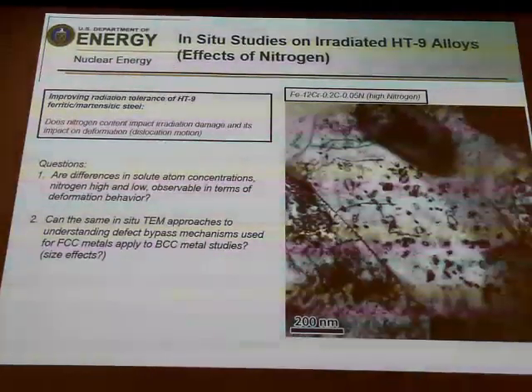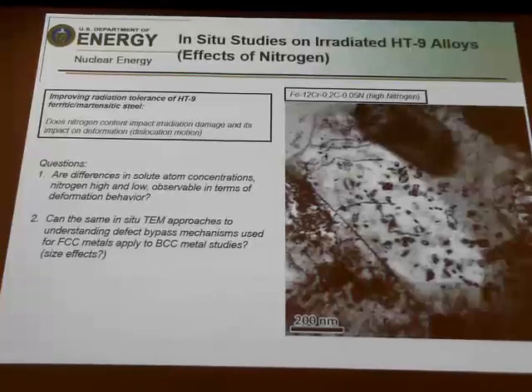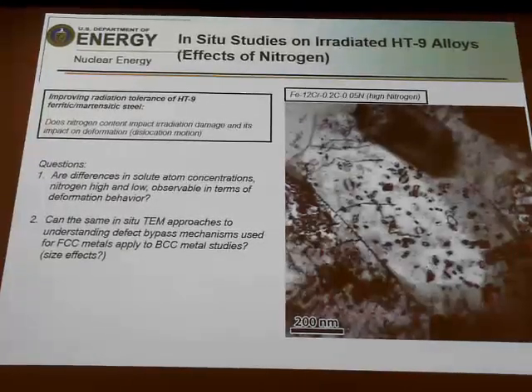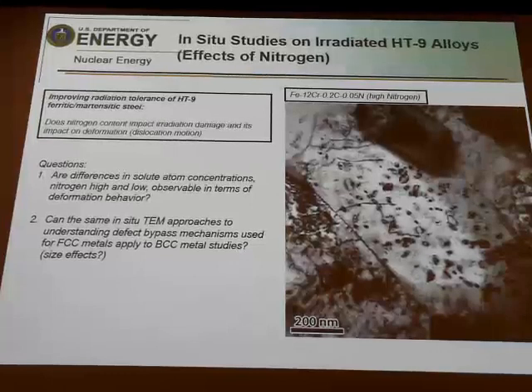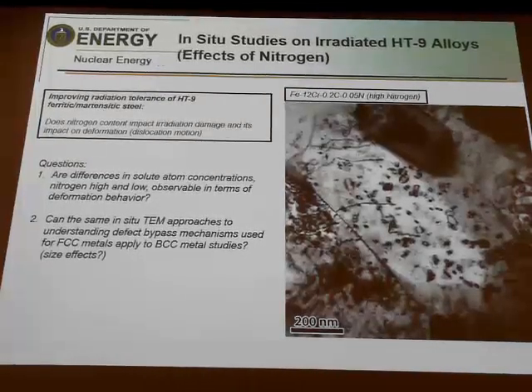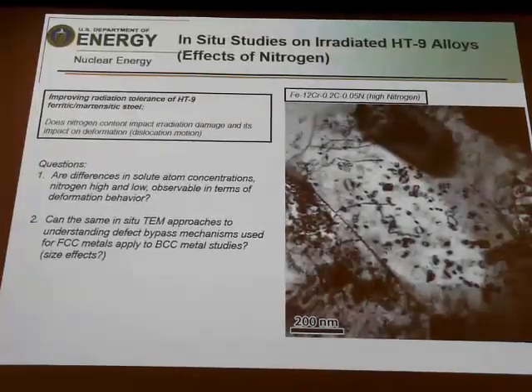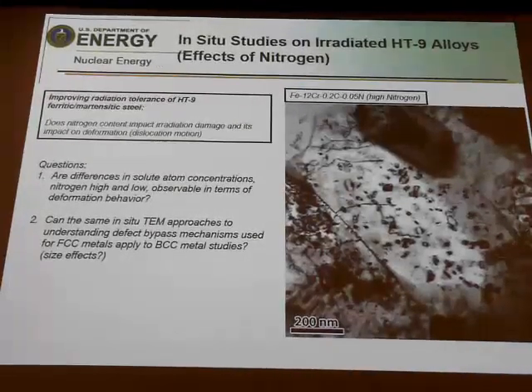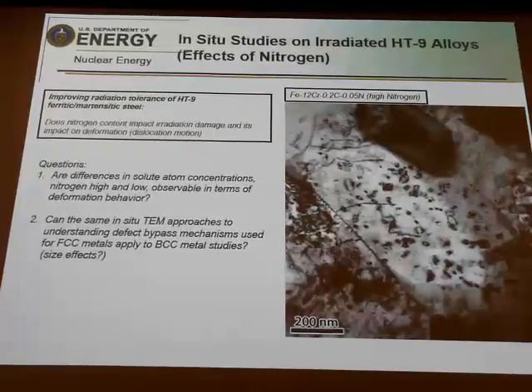So we've taken some materials and made heats that, in this case, is sort of a control material that's got 12 chrome, 0.2 carbon, and 0.05 weight percent nitrogen, and then another low nitrogen alloy that had 0.001 weight percent nitrogen. And clearly what we're trying to look at is, does nitrogen impact radiation damage, but also what impact does it have on deformation? Are differences in solute atom concentrations, like nitrogen high versus low, observable in terms of the deformation behavior?